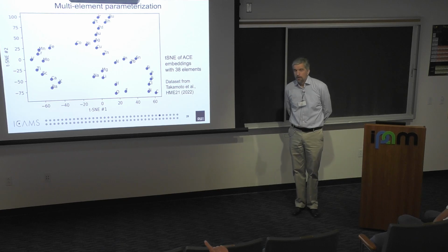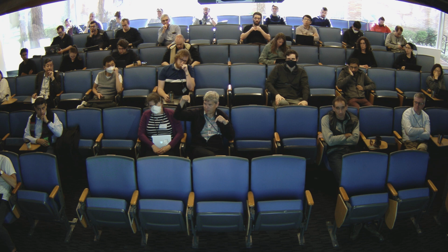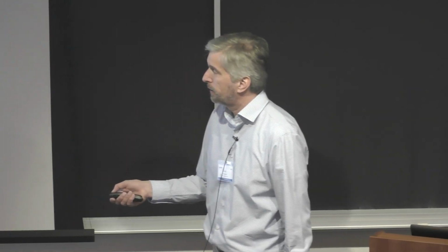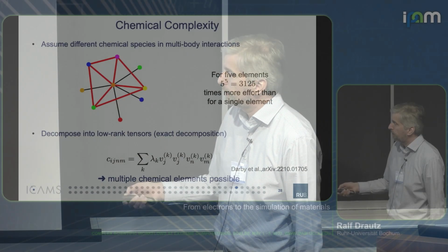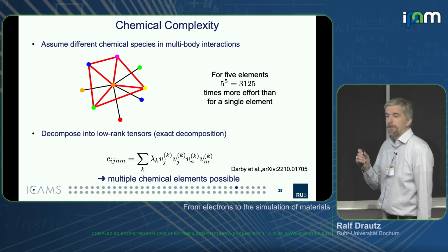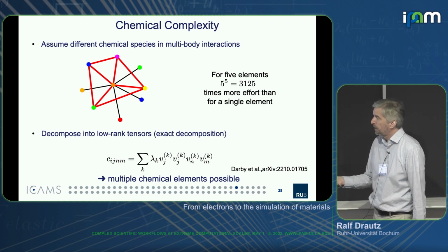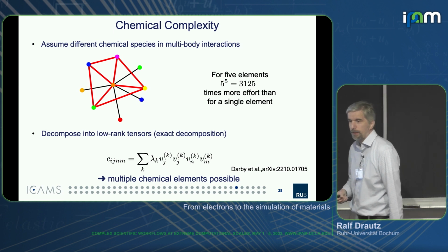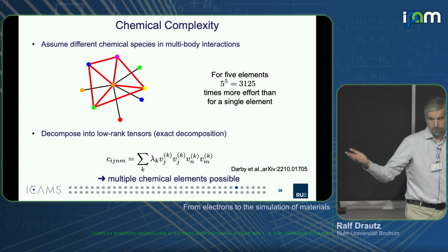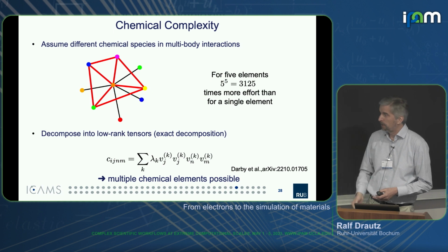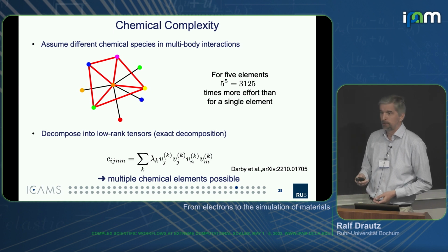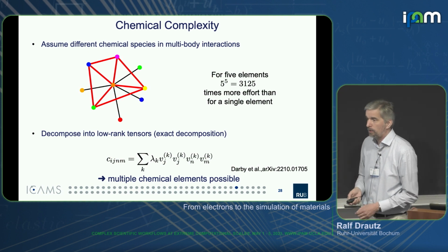So it means you can get your rank 5 tensor into a rank 2 tensor? Yes. So essentially you can stop already at rank 2 for the tensor decomposition. Yes, one can, and this holds for any higher body order. The only thing is that here one only has one and here one has many, right? That's the price that one has to pay. One gets a new axis, but that's just tensor decomposition of symmetric tensors. One can always do that, and it seems to be efficient in chemical space. So that seems to work very well. It's something that we're doing at the moment.